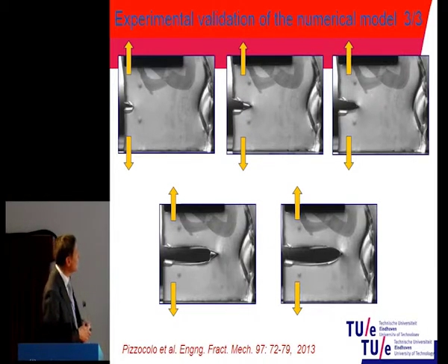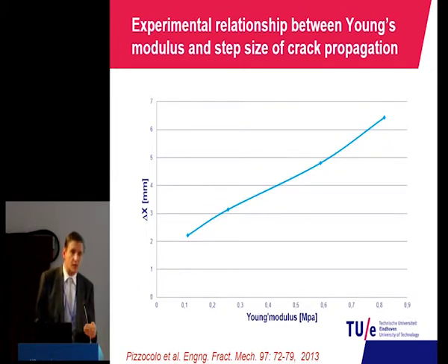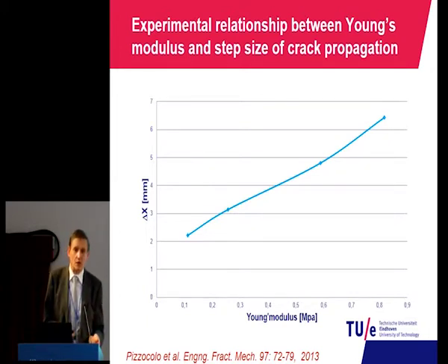Basically, what happens is that as this crack is propagating, the load, which is originally on the right-hand side, distributes over the whole sample beyond this crack, this side is going to be loaded suddenly, and the extra load is first taken up by the fluid and not the solid.